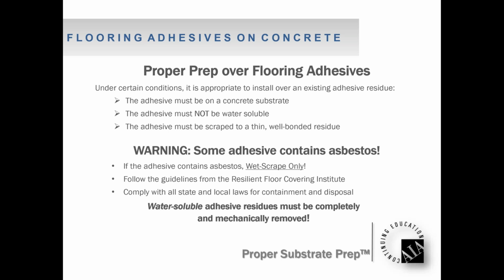So provided the adhesive is on concrete, provided the adhesive is not water soluble, we recommend to scrape it down to a thin, well-bonded residue. This has nothing to do with bond, okay? These patching and leveling products, doesn't matter what manufacturer it is, they will stick to adhesive that still has the notched trowel marks in it from when it was originally installed.